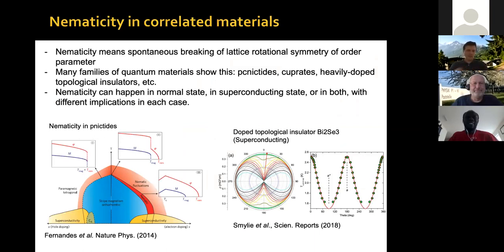Okay? Here I'm showing on the left a typical phase diagram of the pnictides. This is taken out of a review by Rafael Fernandes and collaborators. And you can see that the pnictides is perhaps the system where nematicity has been investigated the most. In that temperature versus doping diagram, you have this nematic region, where you have nematicity in the normal state, and the region above it has nematic fluctuations, etc.